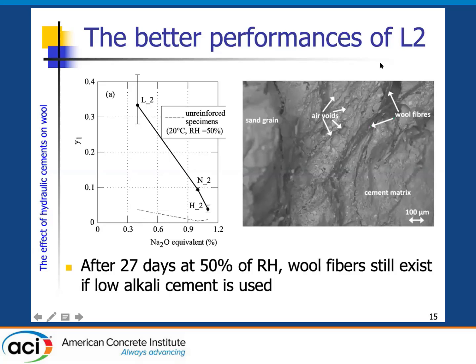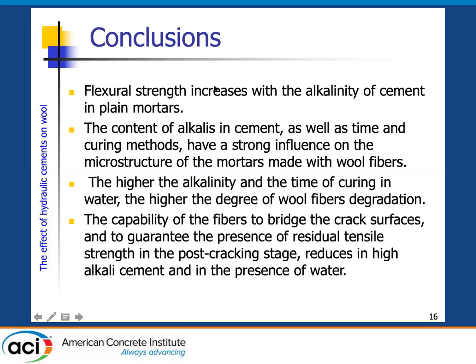Conversely, the better performance of L2 is related to the fact that if you use a low alkali cement, after 27 days outside water, you can still observe the presence of wool. So the wool resists this type of alkali and environment. So these are the conclusions. The strength increases with the alkalinity of cement, and the capability of the fiber to bridge the crack surface can only be guaranteed by the presence of low alkali cement